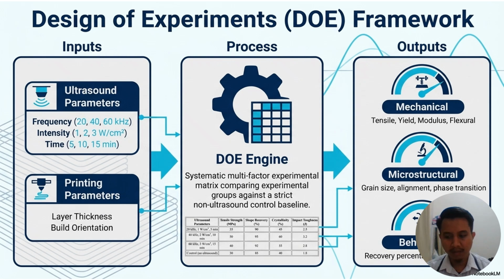The ultrasonic parameters are frequency at 20, 40, and 60 kHz, intensity at 1 to 3 watts per square centimeter, and exposure time at 5, 10, and 15 minutes. The printing parameters are layer thickness and build orientation. This gives us a 3-cube matrix, 27 experimental treatment combinations, each compared against a strict non-ultrasound control baseline.